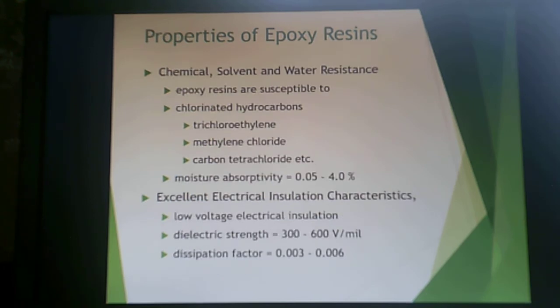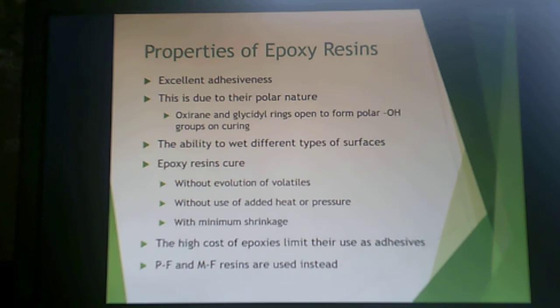Regarding chemical resistance, epoxies can be susceptible to chlorinated hydrocarbons such as trichloroethylene, methylene chloride, and carbon tetrachloride. Moisture absorptivity varies since there are many hydroxyl groups. They generally have excellent electrical insulating characteristics. Epoxies are excellent adhesives because of their many polar OH groups, which interact with and wet many different surfaces. They cure without evolution of volatiles, without added heat or pressure, and with minimum shrinkage, though high cost can limit their use for very large articles.